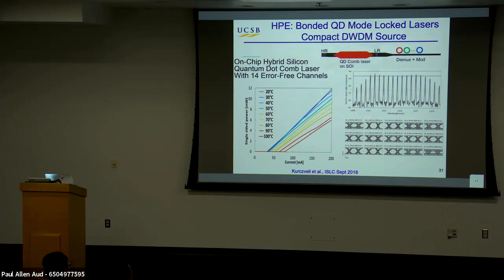So this mode-locked laser puts out a bunch of different mode-locked lines, and you space those at exactly, say, 100 gigahertz, whatever the frequency of your transmission system is going to be. And then looking at the output, these are their eye diagrams, and across 14 channels, they measured error-free operation. And this shows the LI curves, and again, pretty nice high temperature performance, right? At 100 degrees C, there really isn't any change in the slope efficiency here, and it still lases quite nicely with 5 or 6 milliwatts output power.